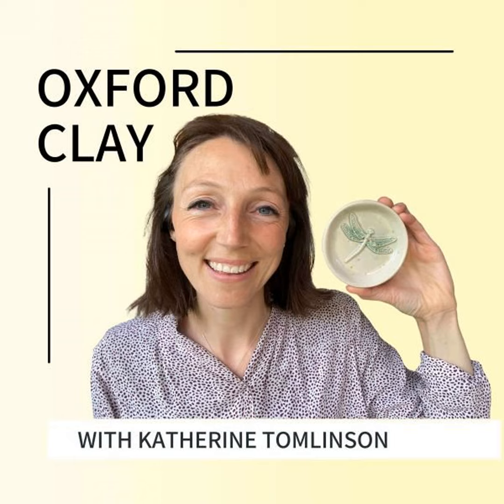The essential process with a press mold is pressing the clay in, and then you gently cut around the side of any overhanging clay. Usually you would use a wooden tool, not a metal tool, because metal tools can actually damage plaster molds. So you very gently cut the sides, and then wait for it to dry, like I was saying, and it will go a bit smaller. Then you can turn your piece out and finish it off, with a bit of sponging, making the base flatter, or getting rid of any sharp edges and stuff like that. So that's a press mold.